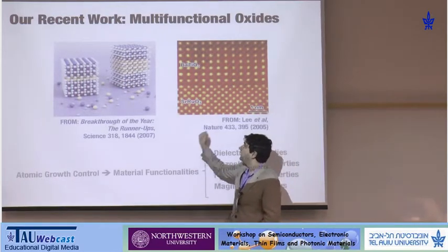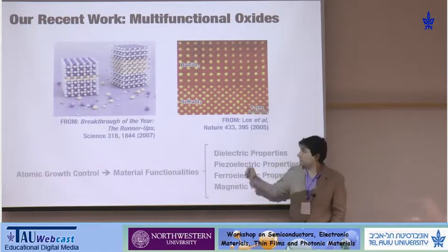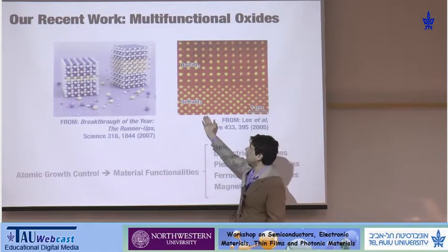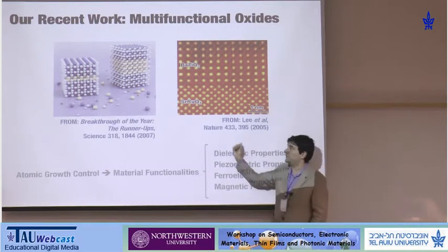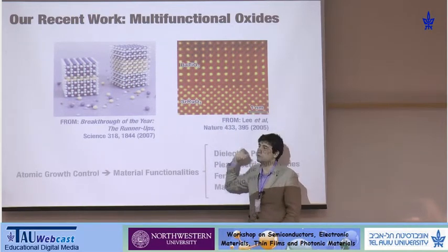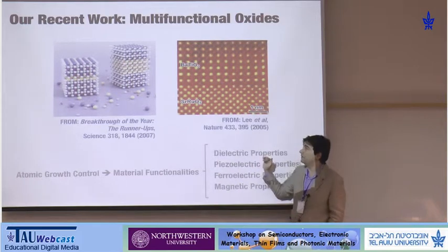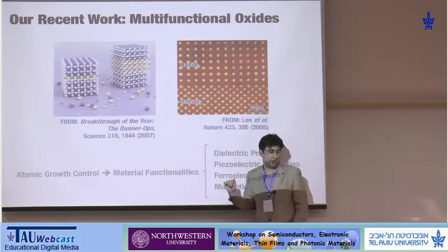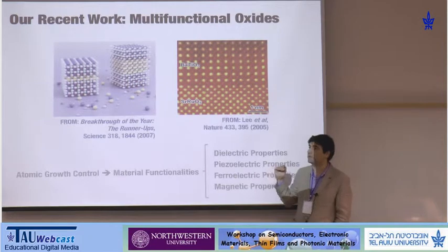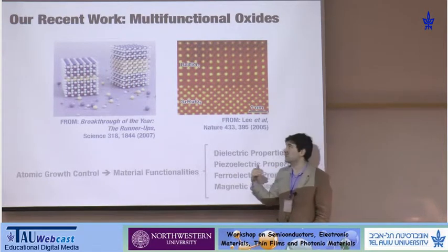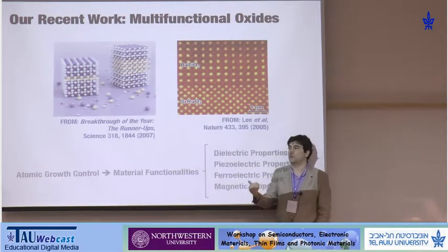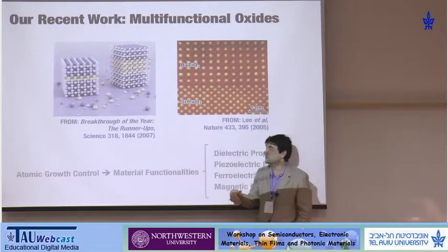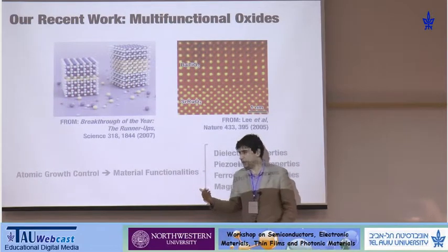This kind of material, and here is an experimental image, high-resolution TEM, of this kind of interface between materials, shows that we have a lot of regularity in them. They can be grown epitaxially and coherently, and this is the perfect kind of system to study with our methods. Because in our methods, we always will have a unit cell that contains the atoms, and we repeat the unit cell infinite times to create a periodic solid.